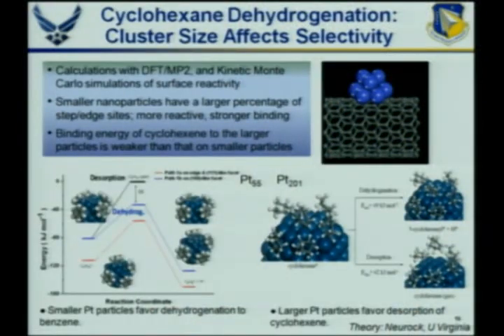In the larger nanoparticles, the cyclohexene doesn't stick as strongly to the large planes on the platinum. So desorption becomes the lowest energy pathway. So here, the cyclohexane sticks, it reacts a little bit, and then desorbs. It pops off the surface. In the smaller nanoparticle, it sticks longer, reacts longer. In the larger nanoparticle, it doesn't stick that long. It just desorbs. So we can model these different types of processes, which are different due to slight changes in the size of the nanoparticle. But what's interesting, it also shows that there are different binding energies dependent on the size of the nanoparticle. So we have size-dependent binding energies.